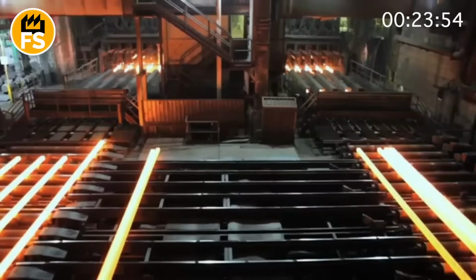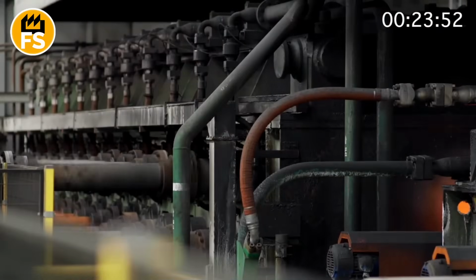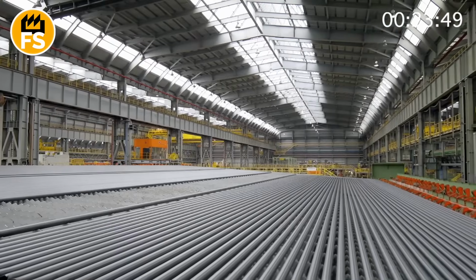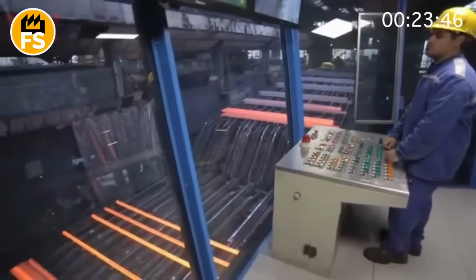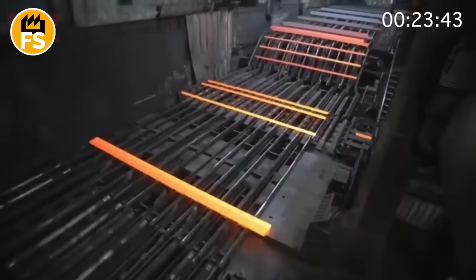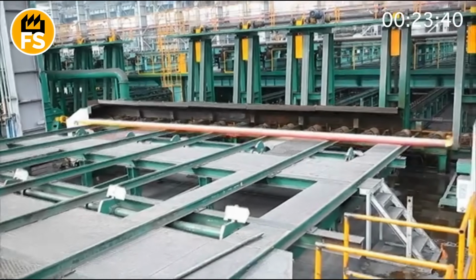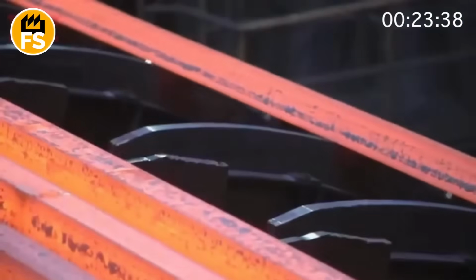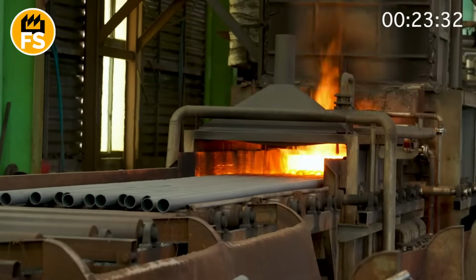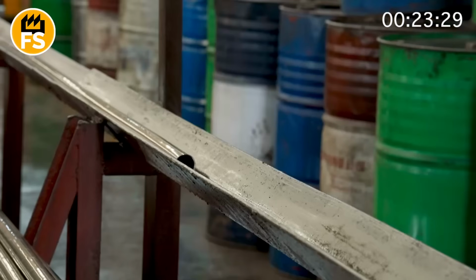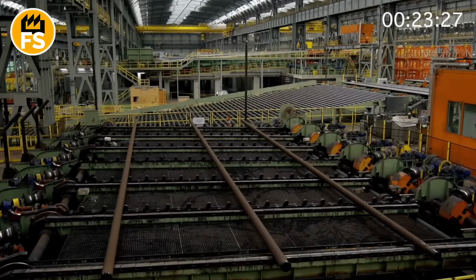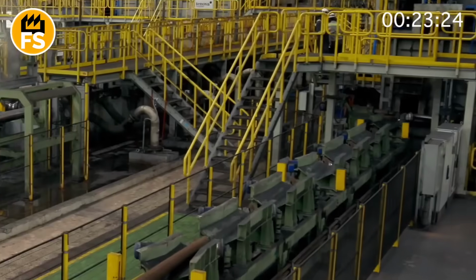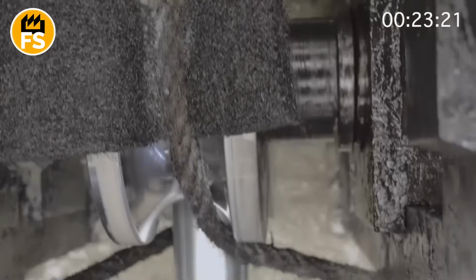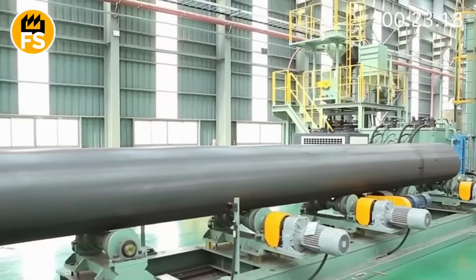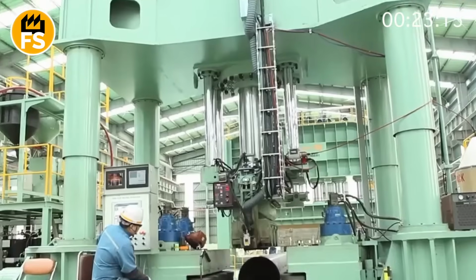At this moment, immense force is at work. The billet is rotated between 2 conical rolls, spinning in opposite directions. The rolls don't just squeeze the billet, they create strong rotational and axial pressure, causing the billet to stretch along its axis, flowing around the piercer point. To avoid cracks or ruptures, the pressure and temperature during piercing are controlled very carefully. If the billet cools too quickly, or the pressure is distributed unevenly, it can break or lose the required shape. Therefore, the process runs without interruption and with strict adherence to all parameters.